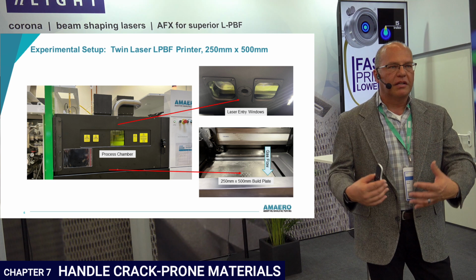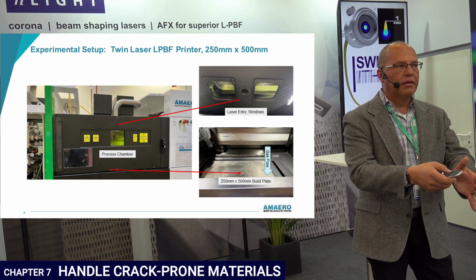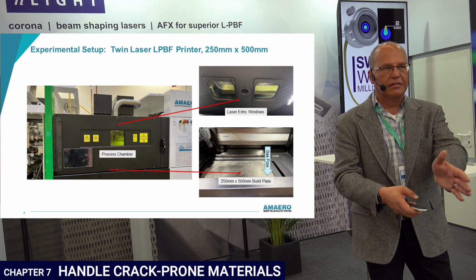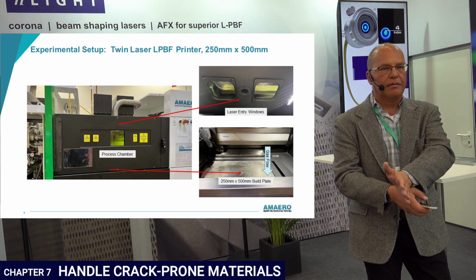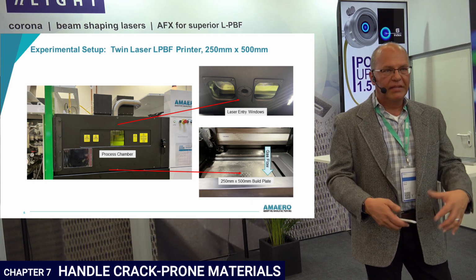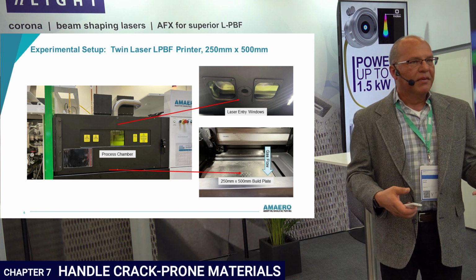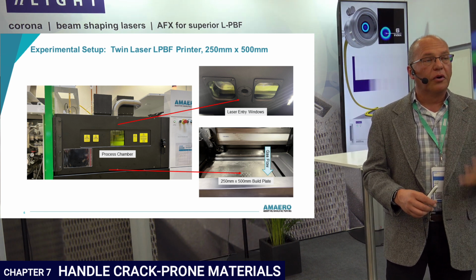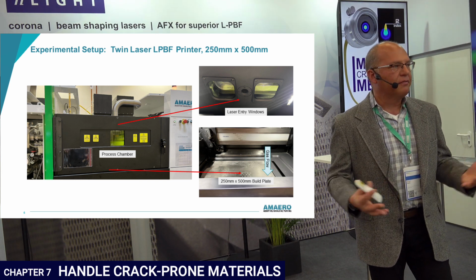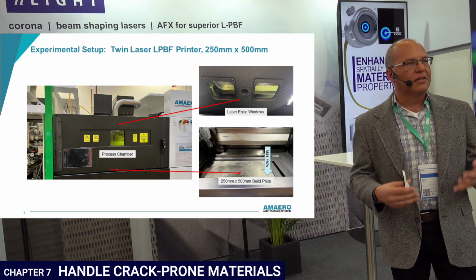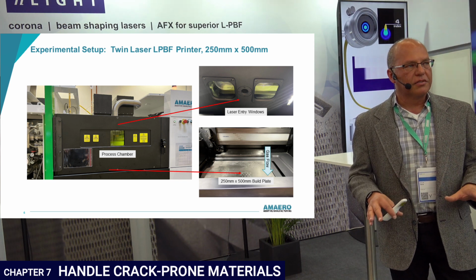But think about printing. We take warm powder, convert it to boiling metal, and then back to consolidated hot metal in like 1 second. That's a very extreme thermal gradient. So we generated a lot of condensates, and we created horrible productivity. We're scanning at like 600 millimeters a second, which is half of a normal scan speed. You do that, and you can create really nice looking H13 microstructure.